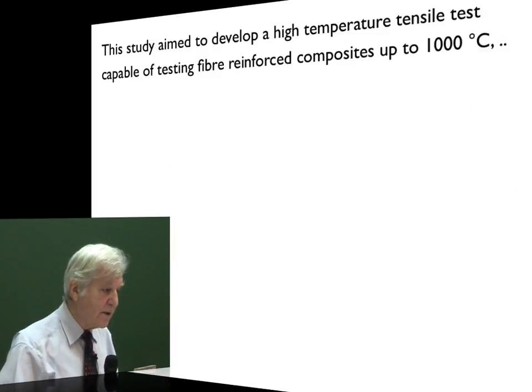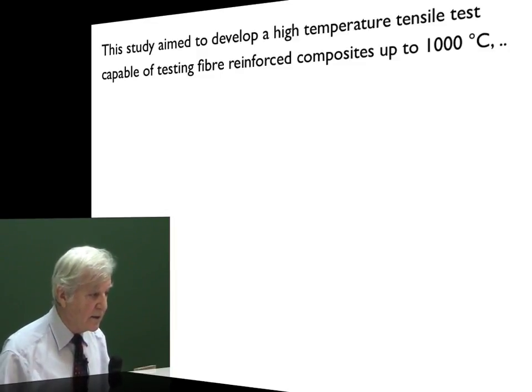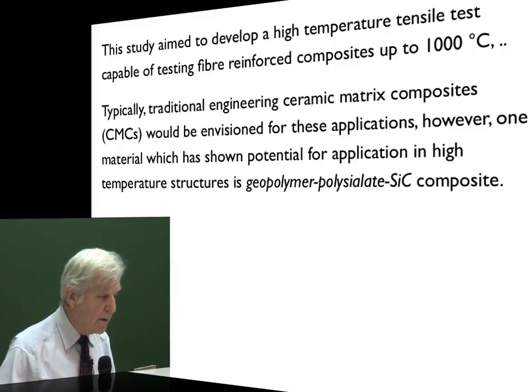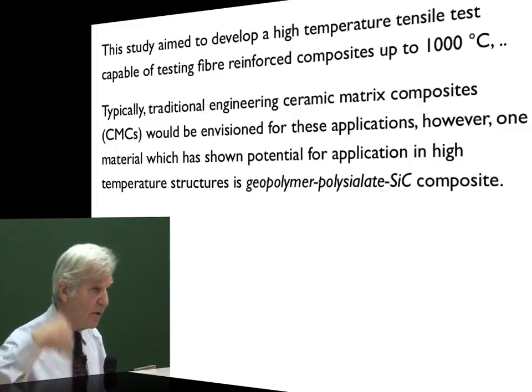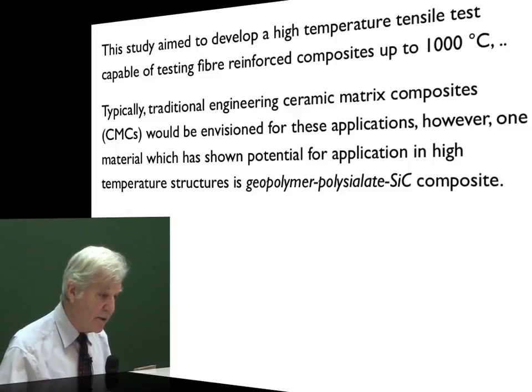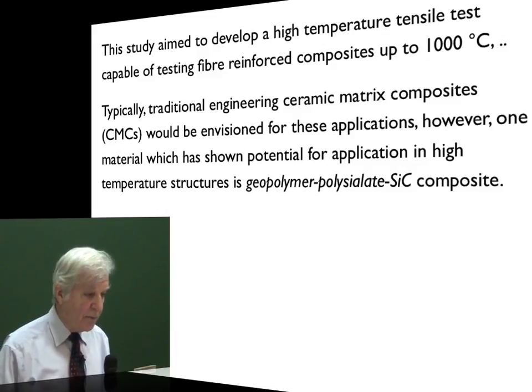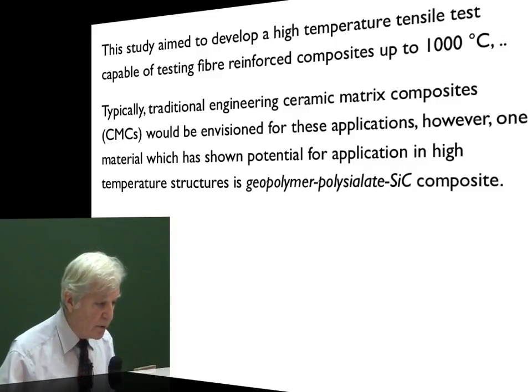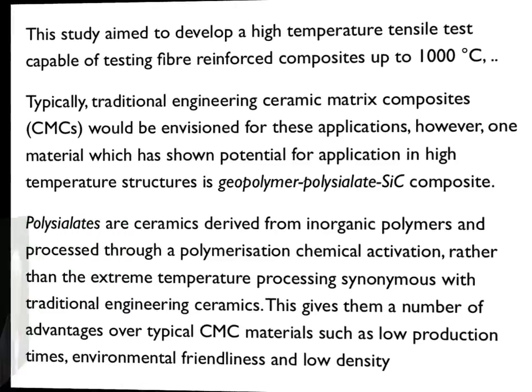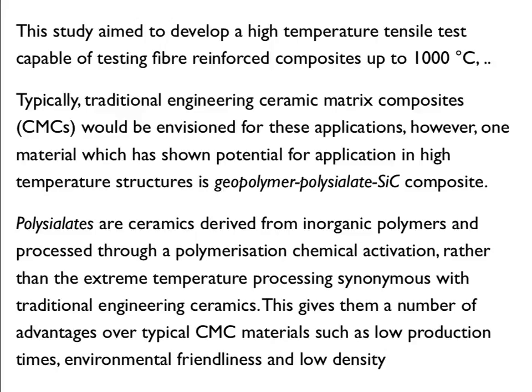This study aimed to develop a high temperature tensile strength test capable of testing fiber reinforced composite up to 1000 degrees C. Typically, traditional engineering ceramic matrix composites, CMCs, those used for high temperature, would be envisioned for these applications. However, one material which has shown potential for application in high temperature structures is geopolymer polysialate SiC silicon carbide composite. Polysialates are ceramics derived from inorganic polymers and processed through a polymerization chemical activation, rather than the extreme temperature processing synonymous with traditional engineering ceramics. This gives them a number of advantages over typical CMC materials, such as low production times, environmental friendliness, and low density.